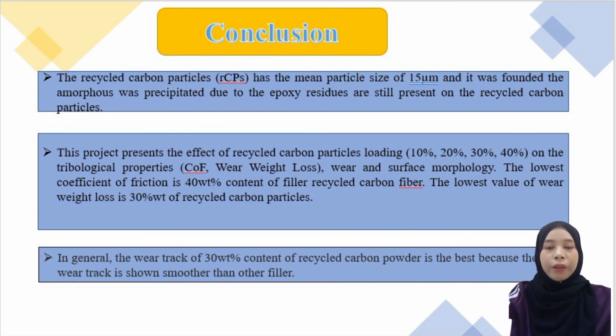The lowest coefficient of friction is at 40% content of filler recycled carbon fiber, and the lowest value of wear weight loss is at 30% recycled carbon particles. So in general, the wear track of 30% content of recycled carbon powder is the best because the wear track is shown smoother than the other fillers.